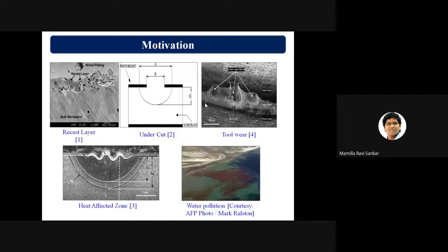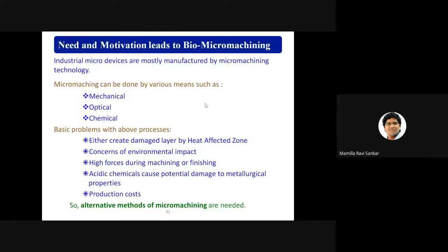To overcome that, one can go with biomicromachining, where your cutting tool is much softer than your workpiece material. There are multiple types of micromachining, like mechanical micromachining such as microturning, micromilling, micro drilling; optical, like lasers, or thermal; and chemical and electrochemical. The basic problems are that they either create a damaged layer like a heat affected zone or recast layer, or have an environmental effect through emissions, for example with electrochemical processes. There are high forces during mechanical micromachining. Chemicals can potentially damage the metallurgical structures of the materials, and production costs will be enormous.